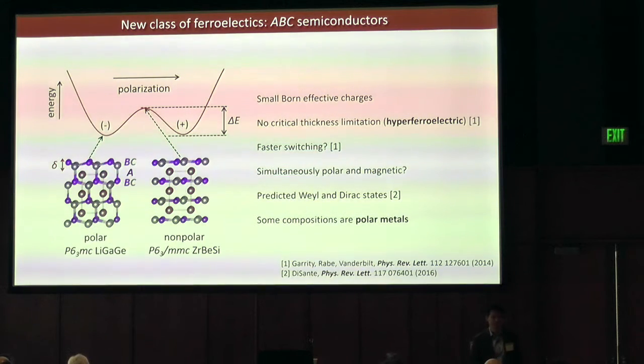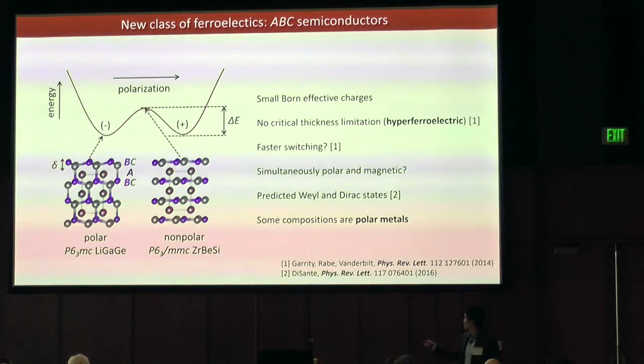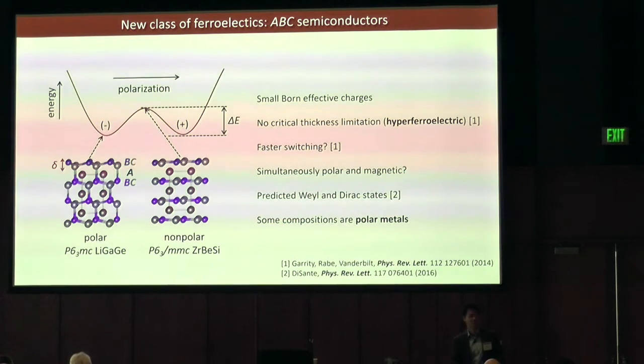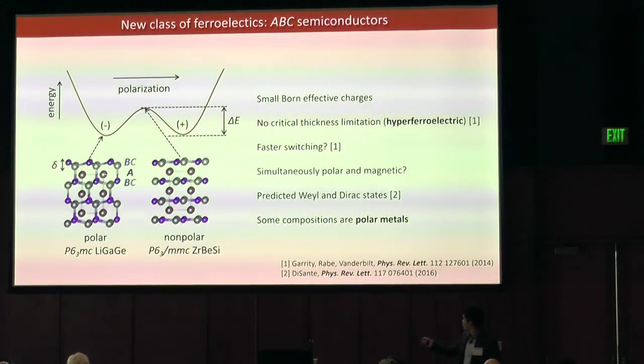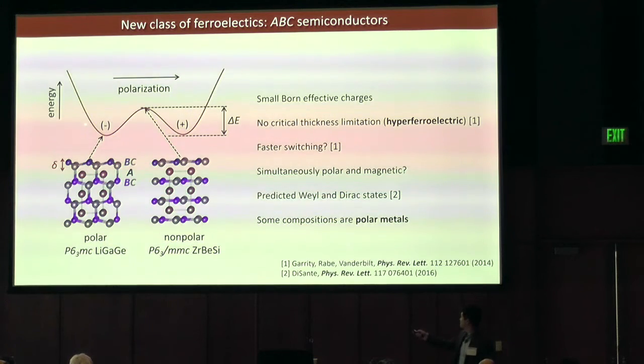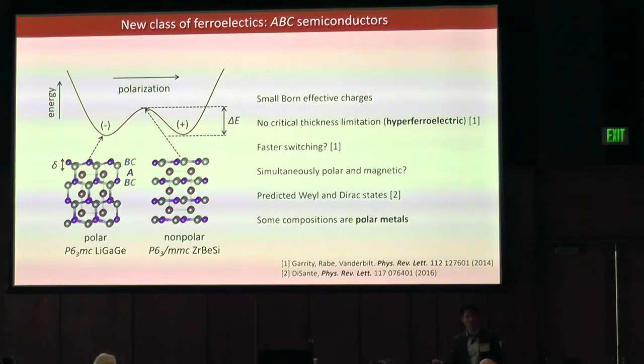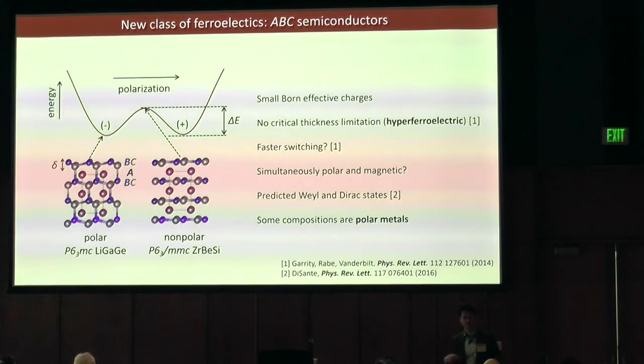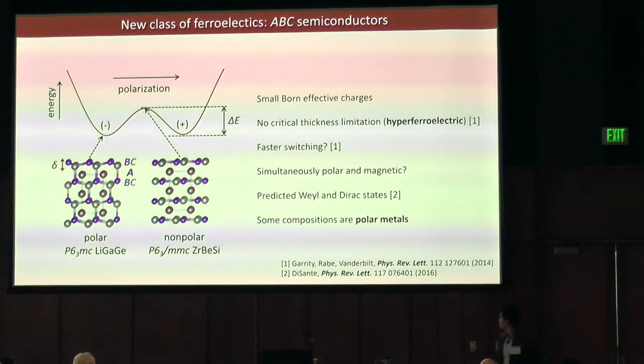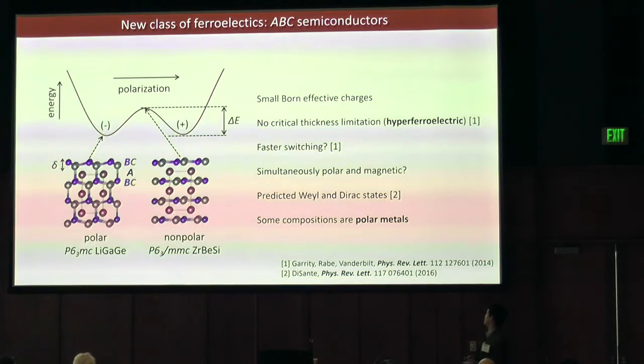And what do these materials look like? Well, in general, they have composition ABC. You can think of them as having a BC sublattice that is wurtzite. You stuff that wurtzite with an A site cation. The polarization is given by the buckling in these BC planes. It's related to a higher symmetry structure where the planes are flattened. So you can sort of think of this as a stuffed graphite structure and a stuffed wurtzite structure. The calculated barriers to switching are similarly small as BTO, and the calculated magnitudes of polarization are similarly large as BTO.